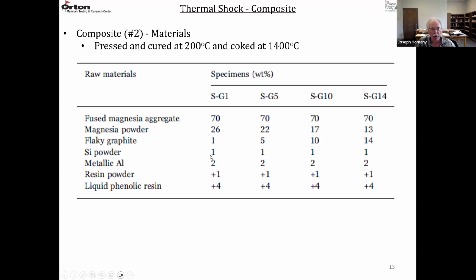There was 1% silicon metal added and 2% aluminum metal. So these are additives. These are anti-oxidation agents. They're basically oxygen getters. They're there to prevent oxidation of the carbon. Theoretically, they react with the oxygen present before it can react with the carbon. The phenolic resin, the powder plus the liquid portion, was 5% in all of these. So when it's coked, there's probably about 2.5% residual carbon. So these powders were pressed. The resin was cured at 200 degrees C, and then they were coked at 1400 degrees C to pyrolyze the phenolic resin.